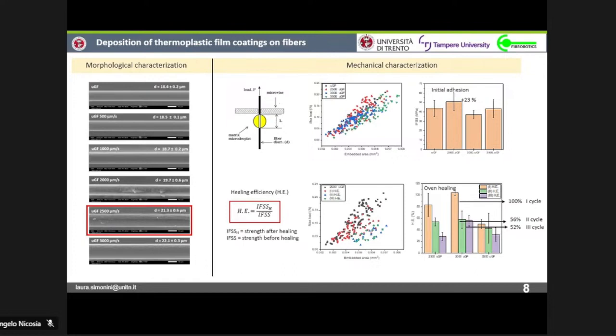We see the linear regression of all of these points in a graph of the load and the embedded area. The slope of the linear regression is the interfacial adhesion. We evaluated a plus 23% increase of the interfacial properties compared to the uncoated fibers. And again, from the microdebonding test, we can also evaluate the healing efficiency as the ratio between the adhesion properties after and before healing.